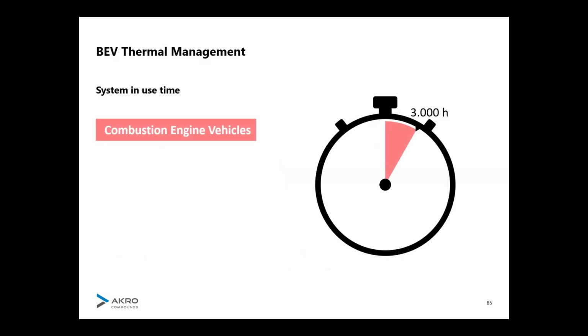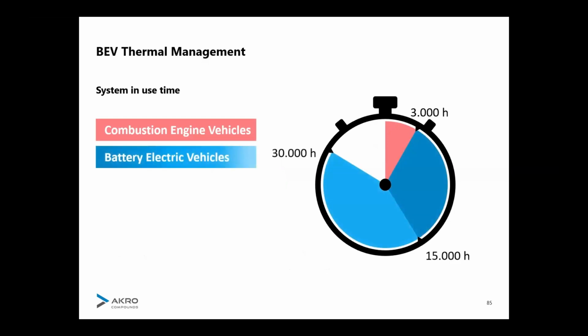weld lines. So I already mentioned the in-use time in a battery electric vehicle is much different from combustion. In combustion engines, we test for 3,000 hours. Now, if you look into battery electric vehicles, 15,000 would be nice. They go even to 30,000, which is already 10 times the in-use time compared to a combustion engine. And we already have customers asking for even more, for 45,000 hours, 15 times the time of a combustion engine. So that makes it necessary that you use really the right material, and